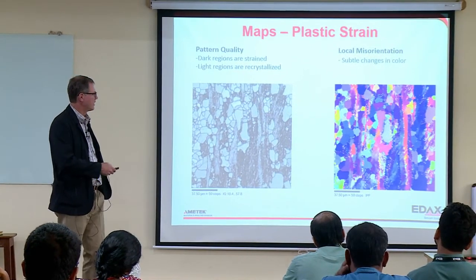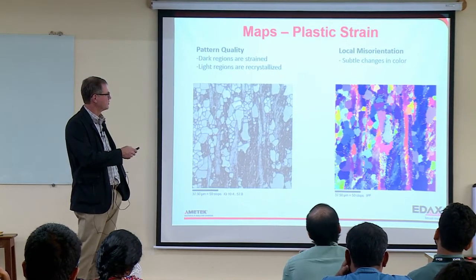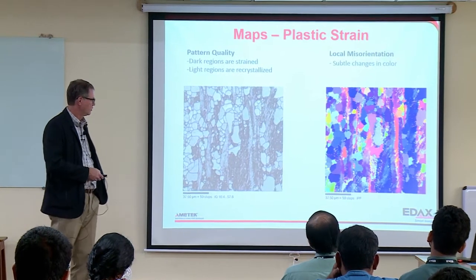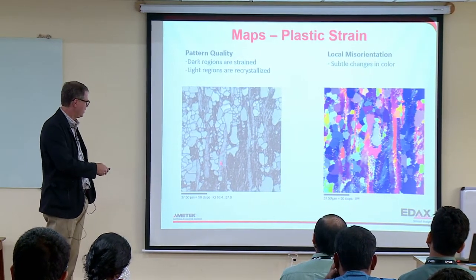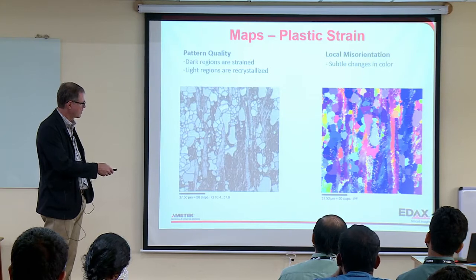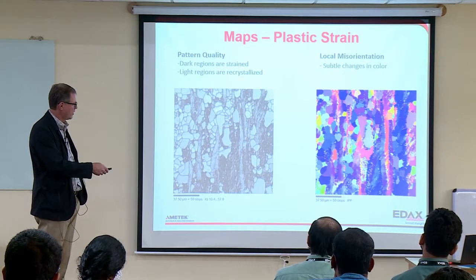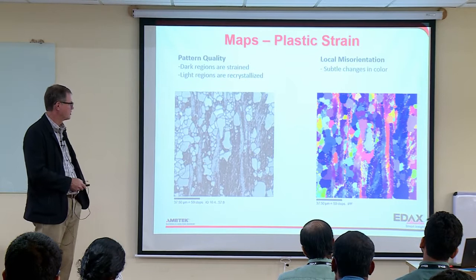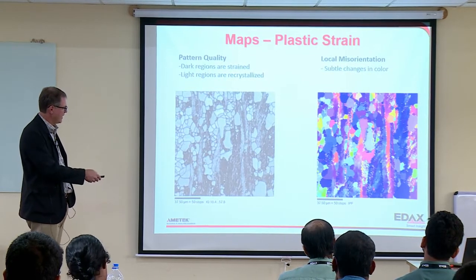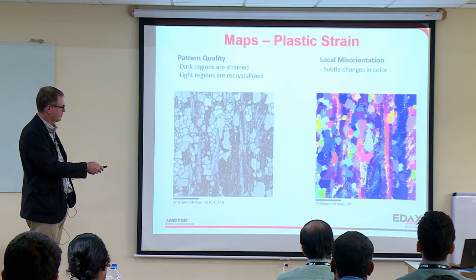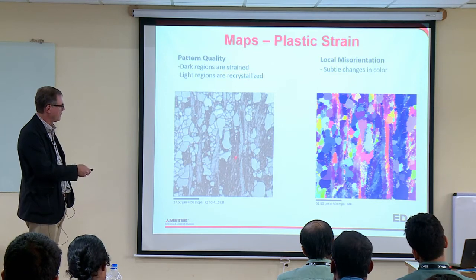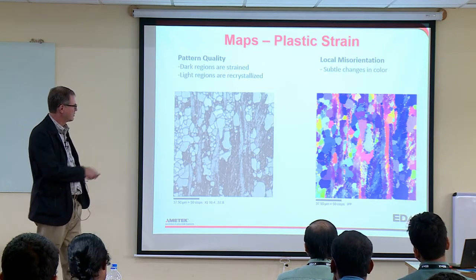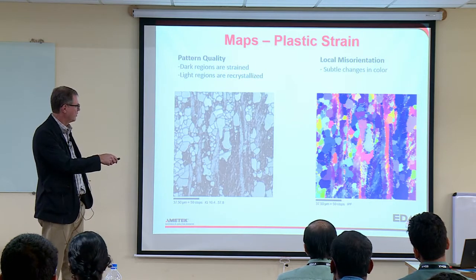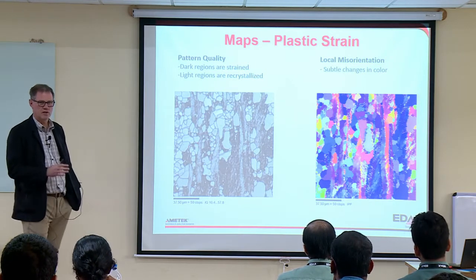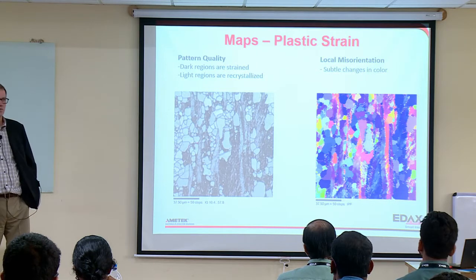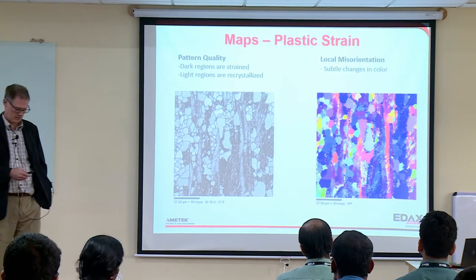We can also look at that if we look at local misorientation, which is subtle changes in color. And you'll notice in this grain here the change in color from almost blue all the way up to red, which is a pretty big change in orientation. You can see bands of different colors within these areas here. But if you look at a recrystallized grain like here, or here, or here, the color's constant. And that's because there's no change in orientation. There's no deformation. There's no dislocations in the material.